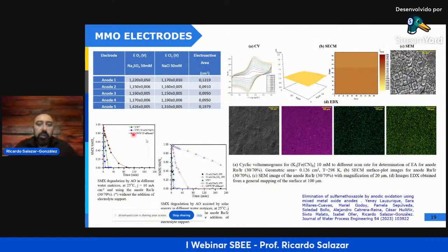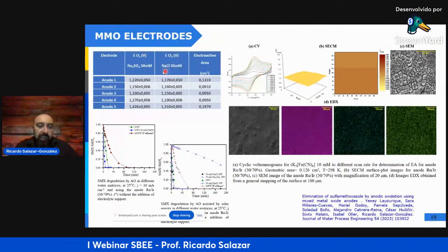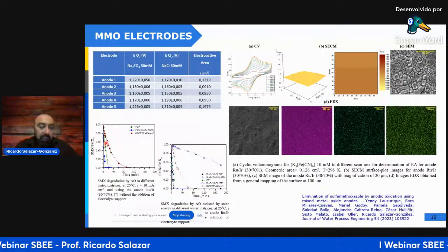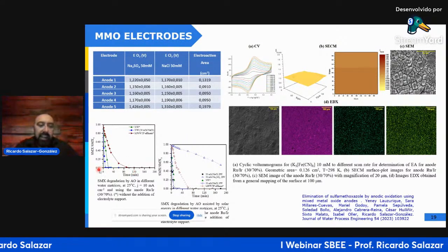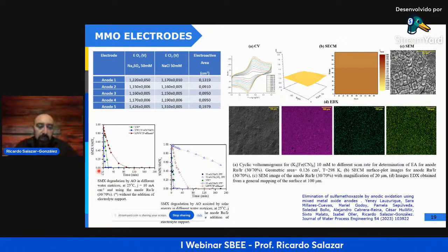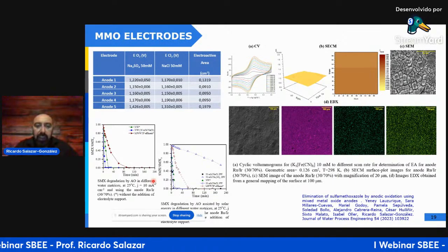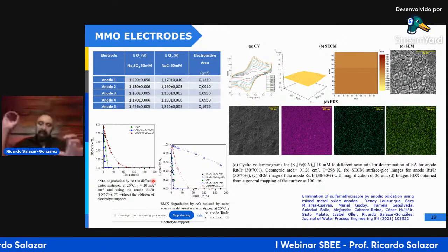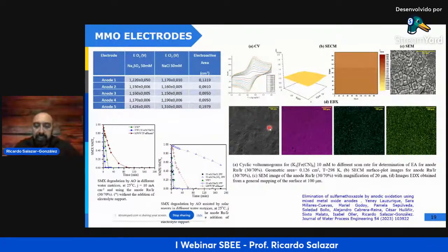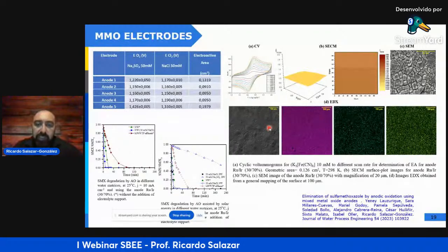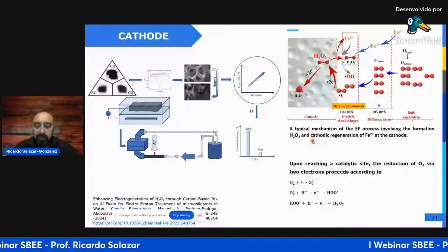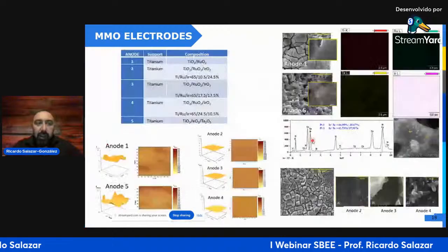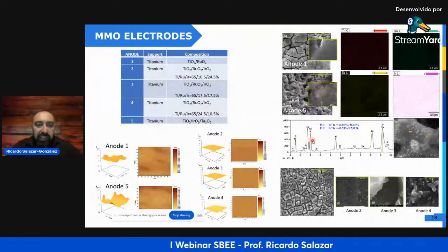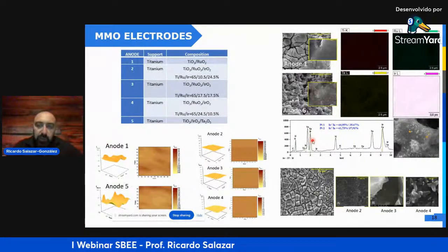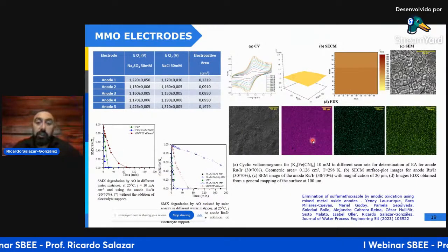And we used this kind of electrodes to treat water containing antibiotic. And you can see a very fast elimination of the pollutant in the presence of chloride in the solution. And this kind of system, you can irradiate it, increasing the degradation of the pollutants in the solution. So you can see different electrodes with different characteristics for the use in oxidation processes.